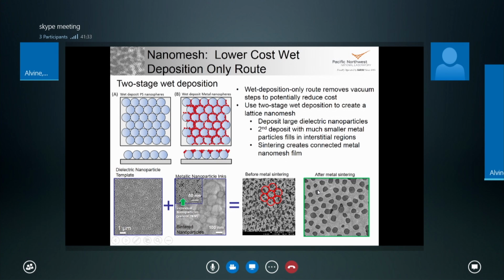Then when you sinter the material all together, you end up with the silver particles sintering together, and you form this metallic mesh. Again, the bright regions are the silver, and the dark regions are the silica spheres that are sticking out of the surface.